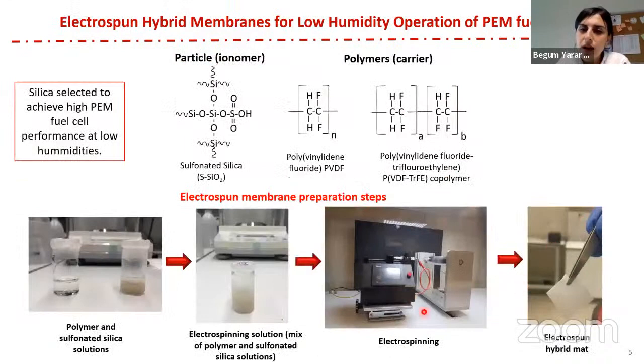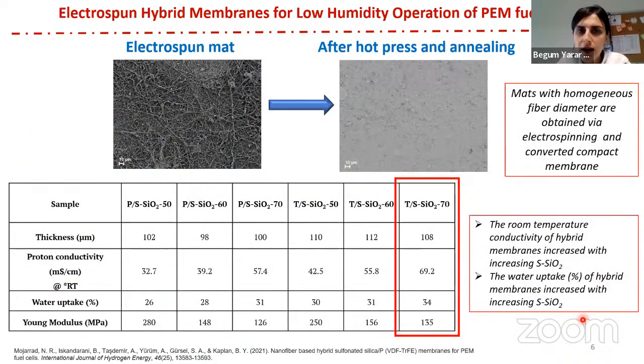Actually, the final product after electrospinning is a mat. Why am I calling this a mat? The final product is a mat because it's porous. For the fuel cell application, we cannot use this porous electrospun mat, so we convert this porous mat to a membrane using hot press and annealing steps, and we eliminate the hydrogen crossover in the fuel cell testing and application.